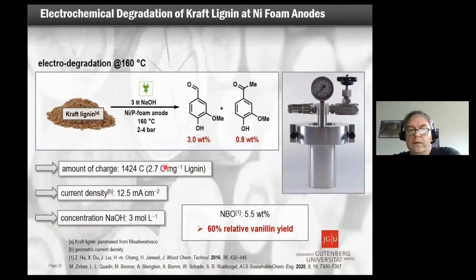to get a very robust process. When we started that and used that, you see these are the nickel foam derivatives we used, and you could even double the previous experiment. It usually comes along with acetovanillone, and if you compare this to the NBO oxidation, that means the nitrobenzene oxidation, it's 60% relative vanillin yield. Therefore, it's already a very good result.